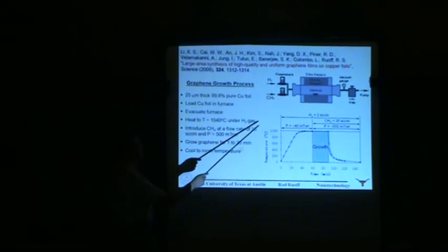So we've been using both cold wall and hot wall systems. This is a so-called hot wall system. It's a simple tube furnace. And this is thermal chemical vapor deposition with precursors like methane. So we have a simple heating regimen under hydrogen. And the goal is to strip off the oxide layer on the copper to expose the bare copper surface. And then to find out, will the methane decompose and leave active carbon species that will surface diffuse or go down into the bulk copper?